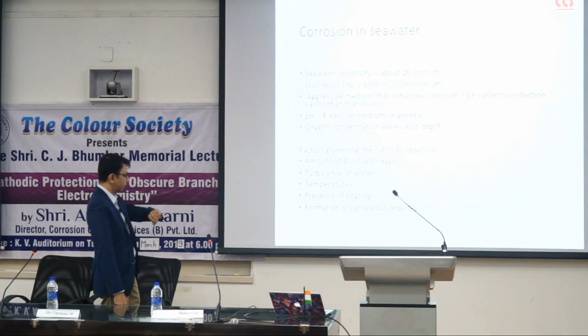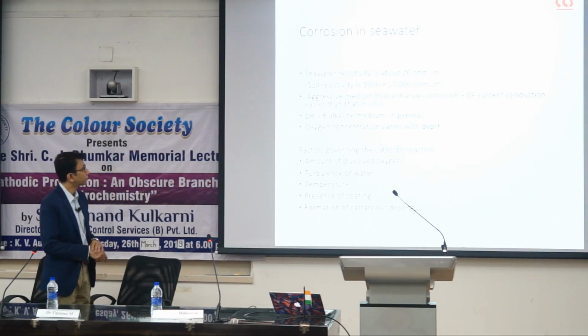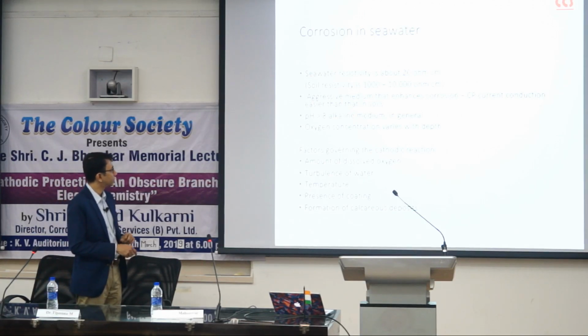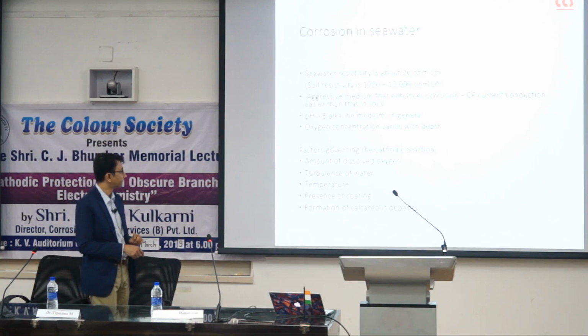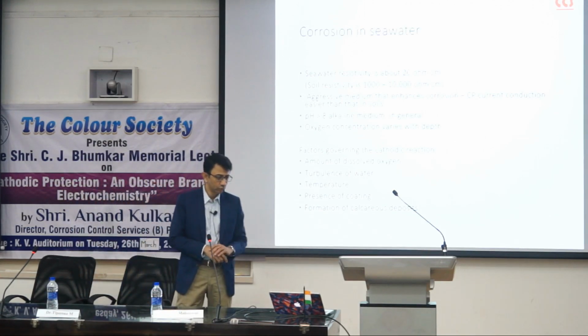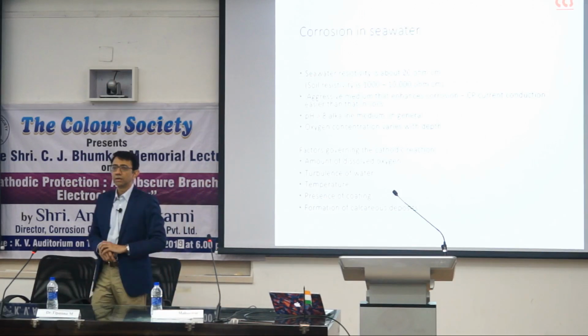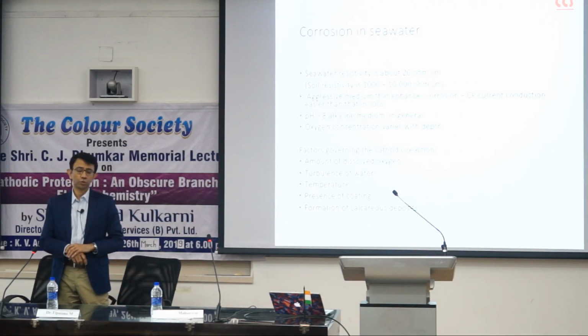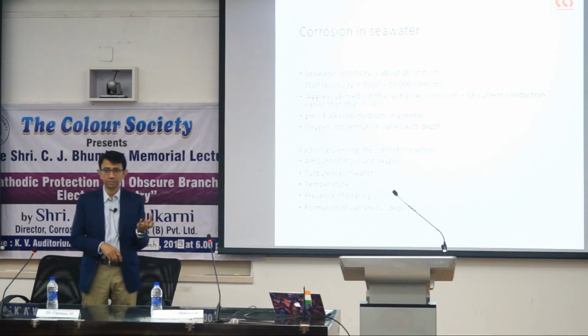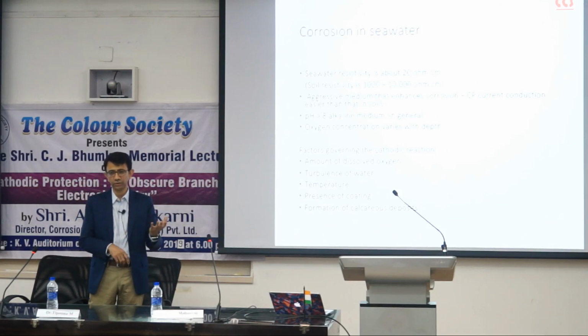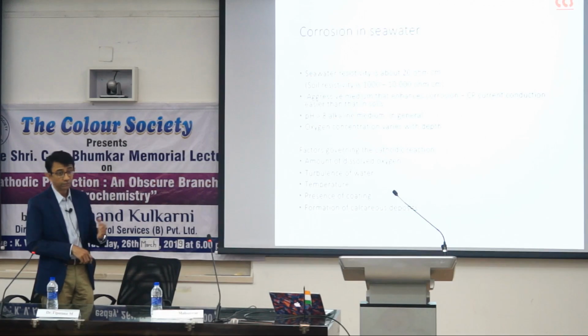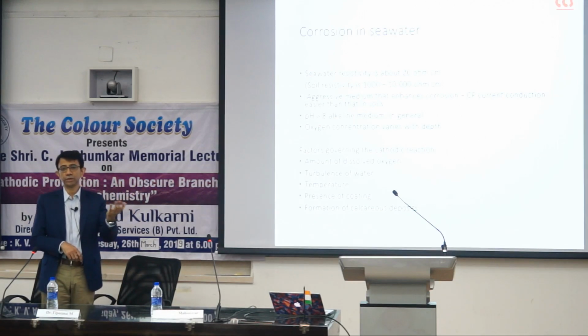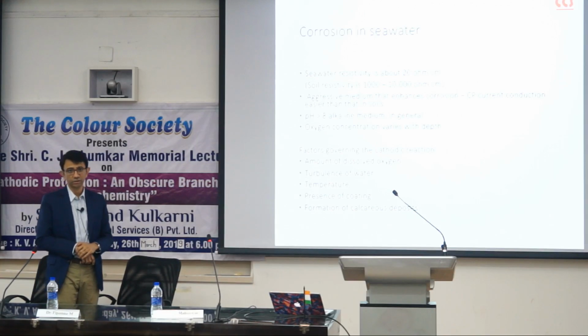A slide on corrosion in seawater. Seawater is about 20 ohm centimeters, very small resistivity, an aggressive medium, high pH, and so depending upon the amount of dissolved oxygen and depending on where the structure is, you're going to have to design the CP system. In the case of seawater, as opposed to on land, we can use small voltages in terms of the DC power units to provide large amounts of current, because we have very, very low resistivity. So we have high corrosion, but the ease with which we can apply current is much better.